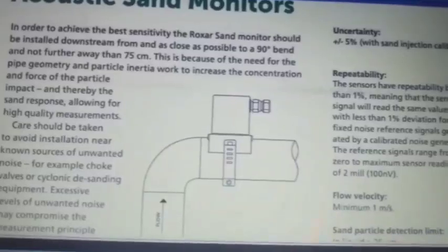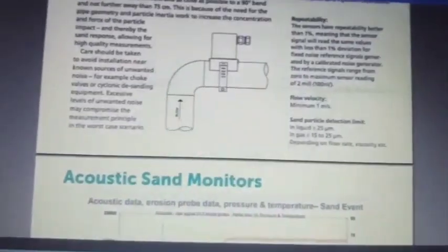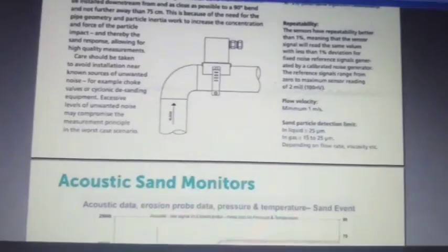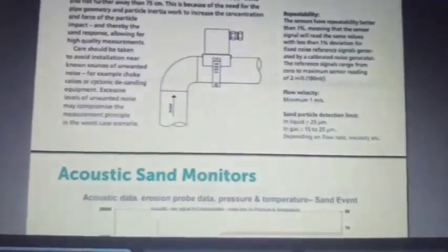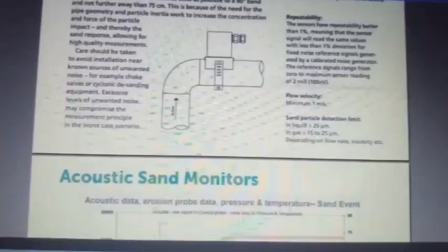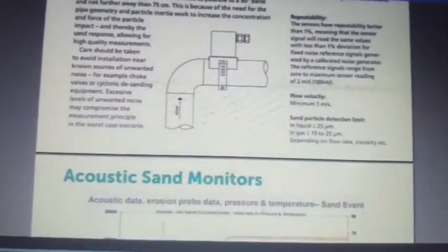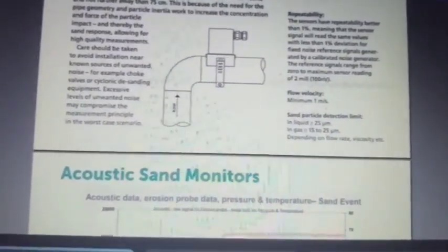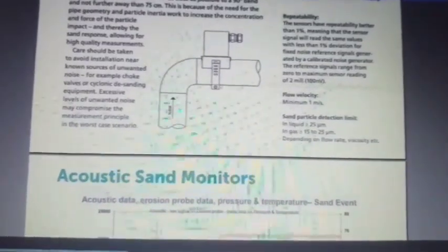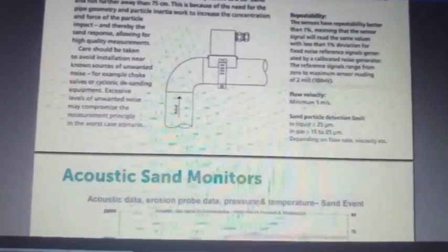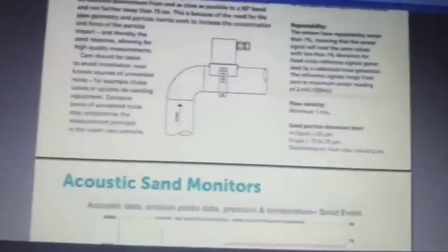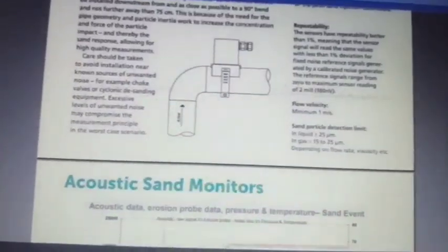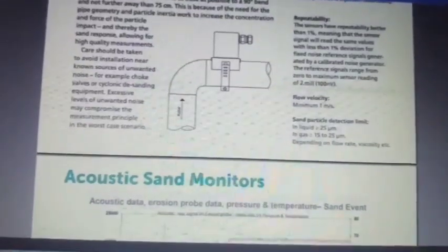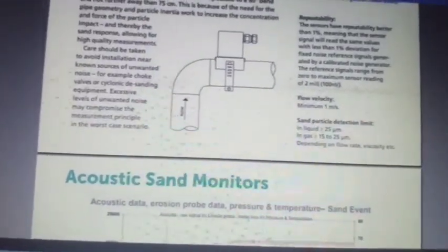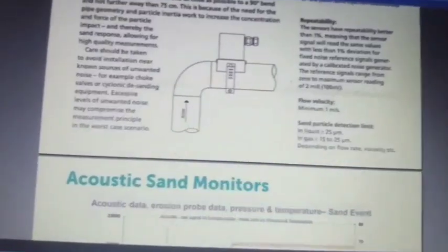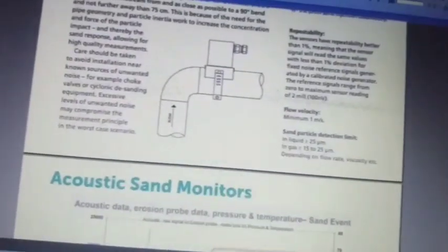What I am saying is, here, the sand particle detection limit in liquid is greater than 25 microns. In gas it is 15 to 25 microns, depending upon flow rate and viscosity. So you are right. Actually, the system has some minimum particle diameter that it can detect. And the corrosivity is greater only after 70 microns. Till 70 micron it will get loaded, but it will not be corrosive or erosive basically. Okay. So that's how it is.